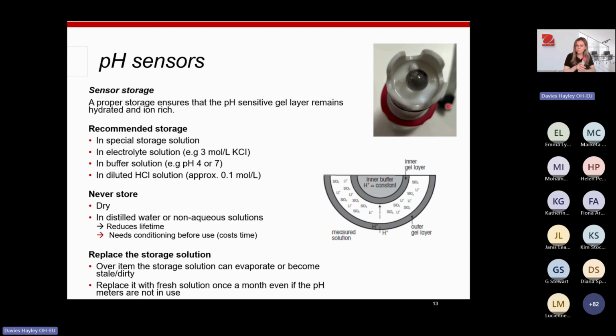How do we store them? Whenever you buy an electrode, it should be supplied with what we call a wetting cap. Our wetting caps have a little tiny sponge in the end, and these are designed to be cleaned and then replaced with the recommended storage solution or electrolyte solution. So you can pop a few drops in there and pop the lid on, and that will make sure it keeps the electrode and the glass membrane nice and hydrated and ion rich. Never, ever, ever store it dry, because you will affect this gel layer.